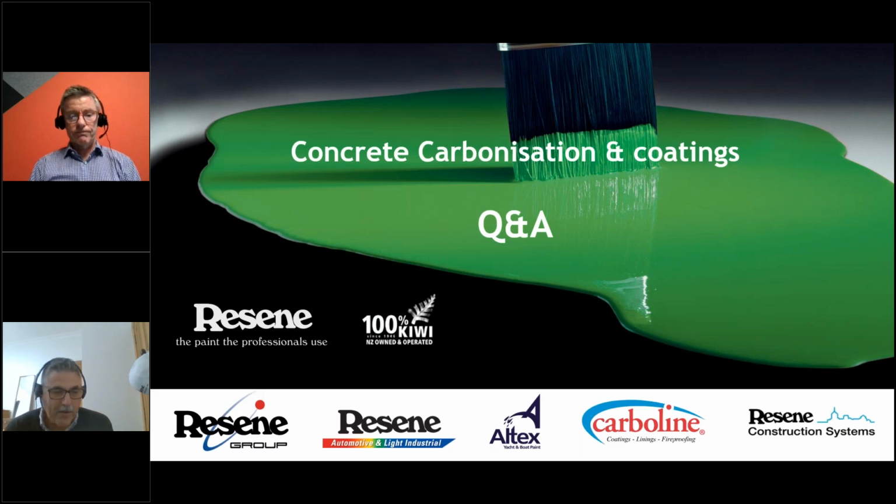Yeah, that's quite a common thing in the 60s and 70s before the advent of modern high build acrylics. Mulseal or different brands of bitumen paints were often used to weathertight concrete structures, and it's a real pain in the neck now because those coatings that have gone over the top have invariably started to fail, as they were not designed to stick to old bitumen coatings. We do have a product called Membrane Primer, which is designed to adhere to bitumen coatings. Ideally you remove all of the loose or weakly adhered coating over the top of the bitumen coating, put the Resene Membrane Primer on it, and then recoat it. But it can be an ongoing problem. It's not an easy fix.